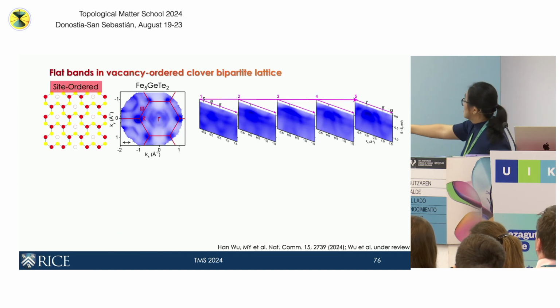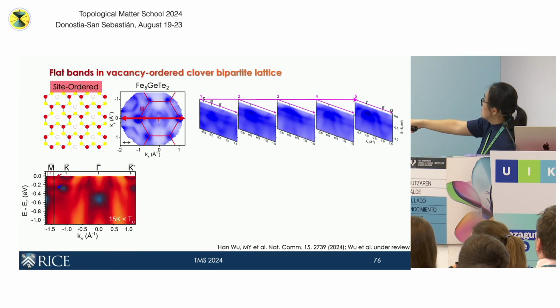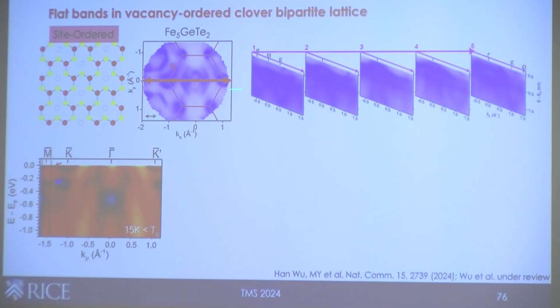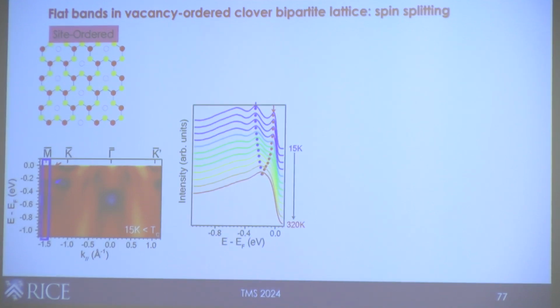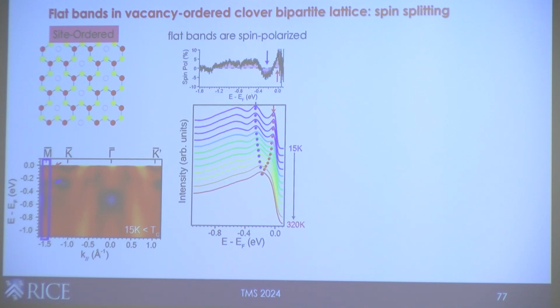So just a reminder, this is the flat band phase. We can see that from this Kagome lattice. And what we can do is track these flat bands as a function of temperature. The way we do that is we take a cut here, a vertical cut. This is the place where we only see the flat band. If you see one of these, it has a hump. That's this flat band. Next hump, that's this flat band. And if we track this as a function of temperature, you can see that these two peaks merge together.